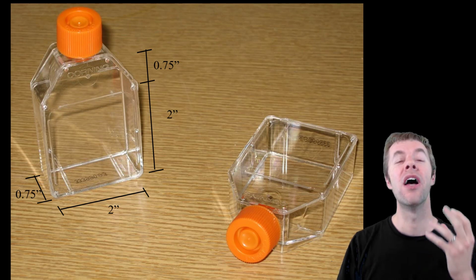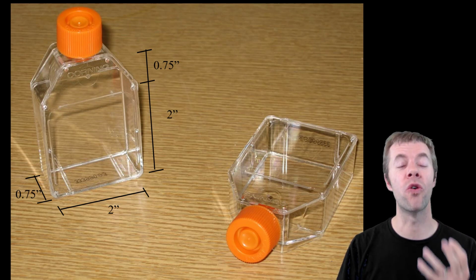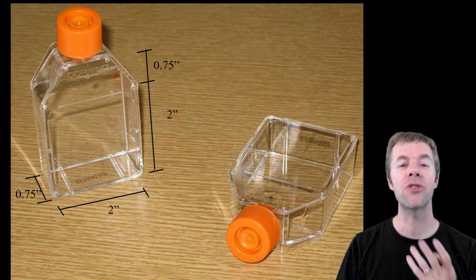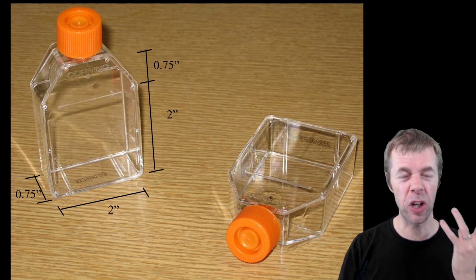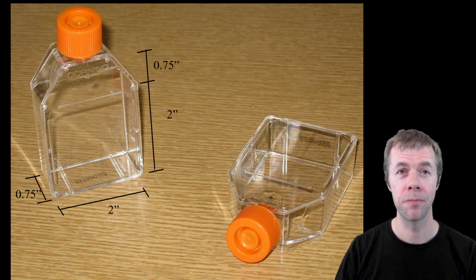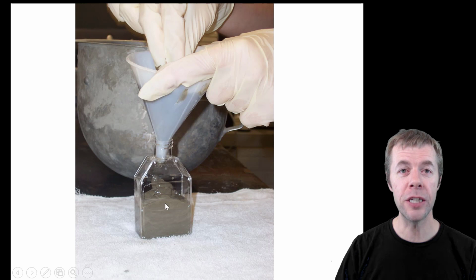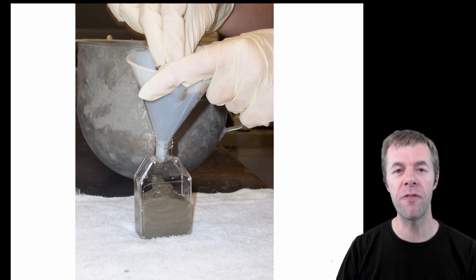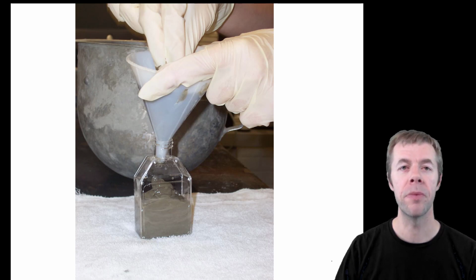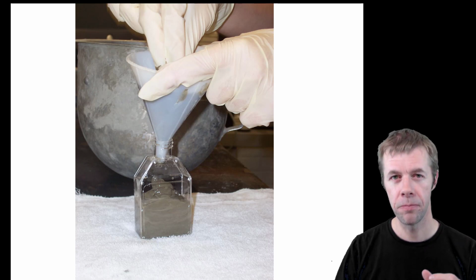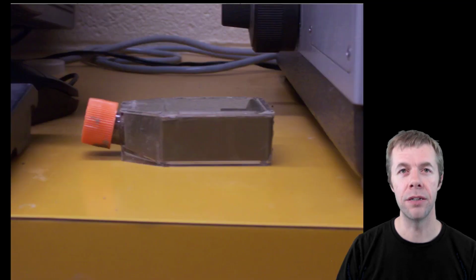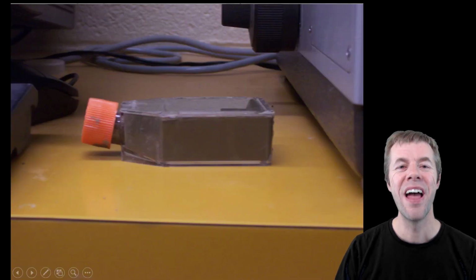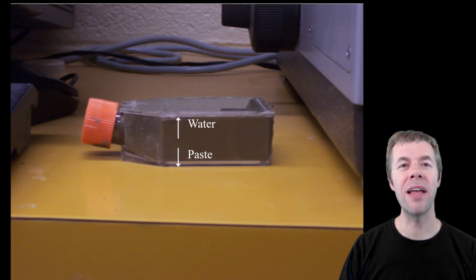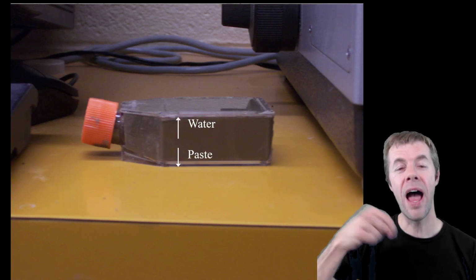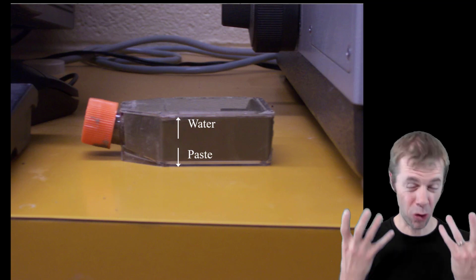Just kidding. I started out trying to prove or learn more about air-entrained concrete, using these bottles that were optically clear. You can see right through them. I filled these bottles full of air-entrained cement paste, but not all the way up. Then I put the lid on and turned them over on their side. Over time, the cement is going to go to the bottom and the water is going to go to the top. This is called bleeding.